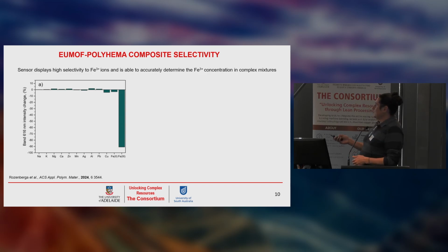But you can see in the presence of all these other ions, so different ions from alkali metals here up to transition metals, and copper as well, very important, that we see very little change in the emission signal from the composite. So this is very good. It's very sensitive to ferric ions, very insensitive to these other ions, so it's quite selective.